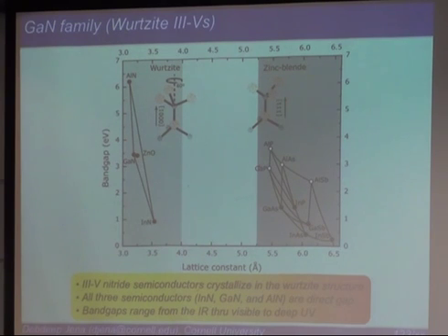And as a result, this structure has what you call cubic symmetry. You can show that if you go this way or along the x, y, z axes, it all looks the same. But here it looks very different if you go in this direction than that direction. So this 60-degree rotation is only along that direction, not in the other two. So this is called a uniaxial crystal.